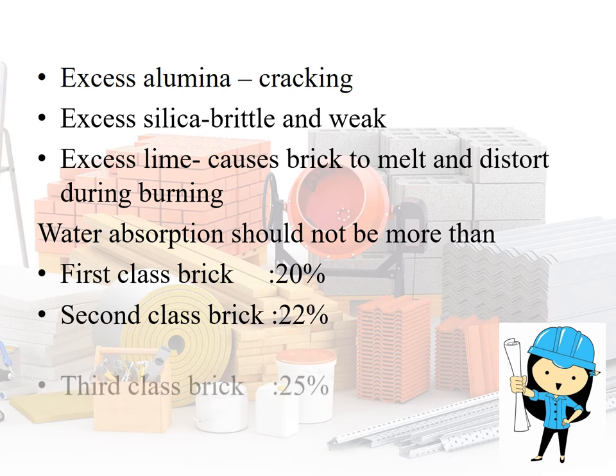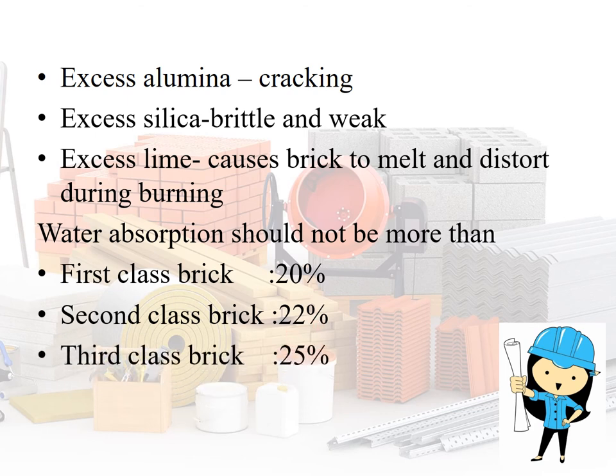Now for water absorption conditions: for first class brick, it should not be more than 20% of its dry weight. For second class brick, it should not be more than 22% of its dry weight. For third class brick, it should not be more than 25% of its dry weight. These points are very important in all MCQ exams and are repeatedly asked questions.